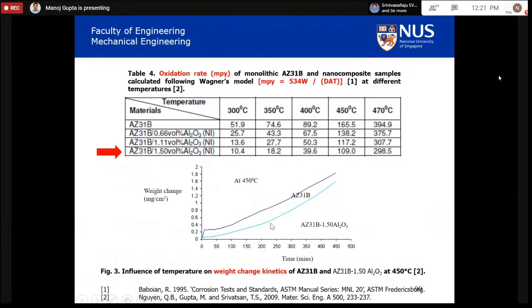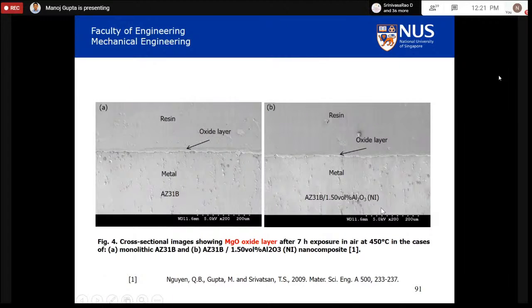The weight change is always lesser than the unreinforced material. So putting a reinforcement improves oxidation resistance by reducing the thickness of the oxide layer and making it more compact. And this happens because by putting the reinforcement, you refine the microstructure, and similar studies have been observed by researchers in Australia, where they observed in stainless steel, just by refining the microstructure, you can improve the corrosion resistance of